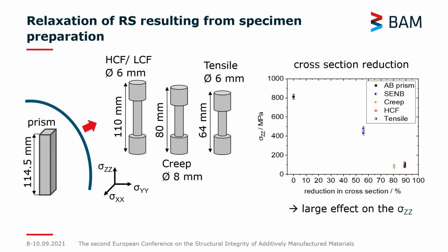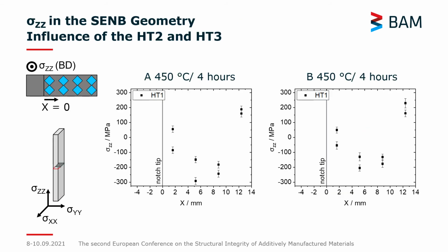Now, how does this compare to relaxation using different heat treatments? We are now analyzing the effect of heat treatments on the residual stresses in the SENB geometry. As you can see, we determined the residual stresses along two measurement lines in the notch plane of our SENB specimens. We plotted the residual stresses in the build direction versus the distance from the notch tip. And what we've observed is that closer to the surface, we have tensile residual stresses that are balanced with compressive residual stresses. In the vicinity of the notch tip, we also see that there's a delta between the two measurement lines. Now, what happens when we apply 800 degrees for 1 hour?